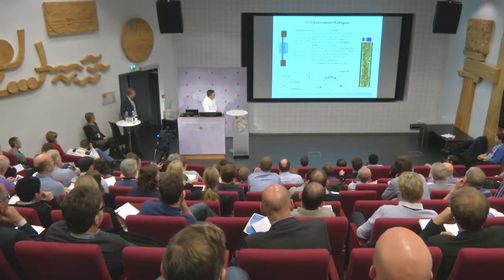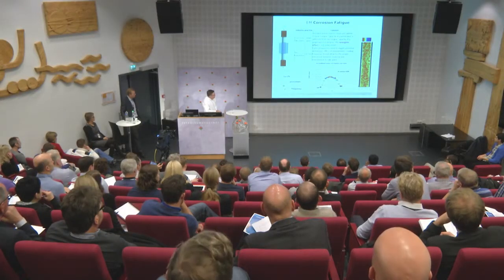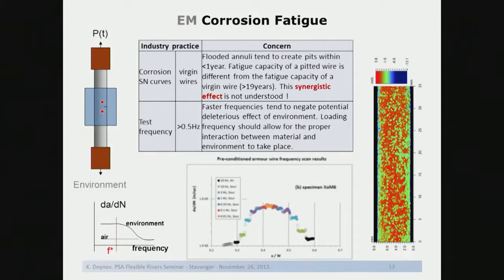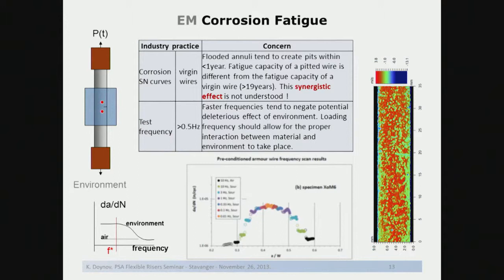So we start with testing at 10 Hertz in air, then 10 Hertz in a sour environment, followed by 3 Hertz, 1 Hertz, up to 0.01 Hertz. And then we're increasing the frequency backwards, simply to clearly see this effect. What is shown here on the right-hand side of the picture, we spent some time to learn how to acceleratedly pre-corrode the wires and put some pits in it. Then this picture really represents a scan with white light interferometry that characterizes the pits. So we learned how to characterize them statistically. Now we're in the process of doing fatigue testing to correlate the different pits with the fatigue resistance of the wires.